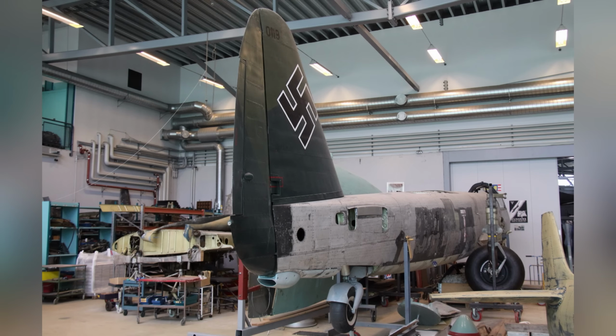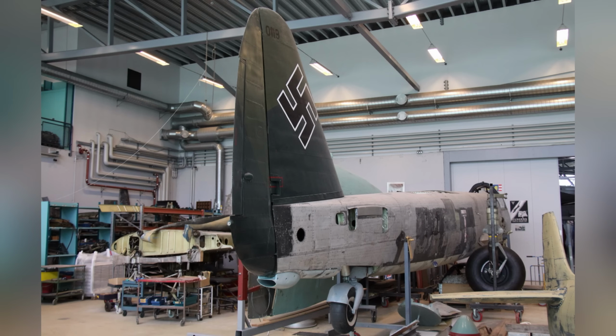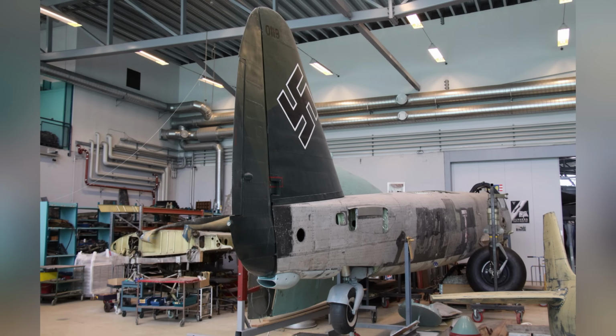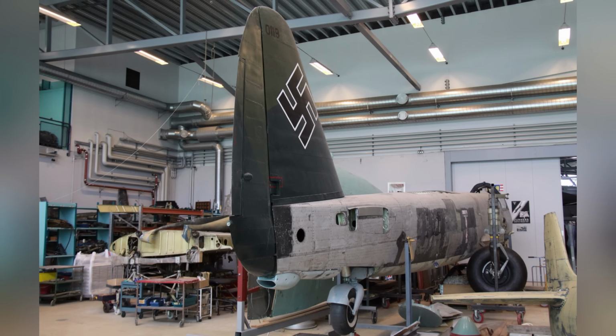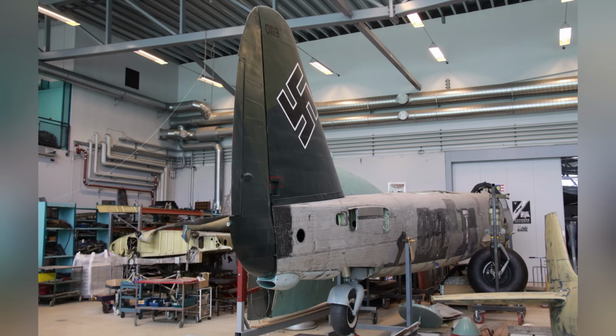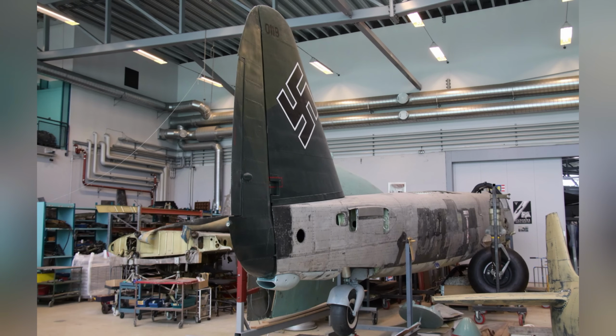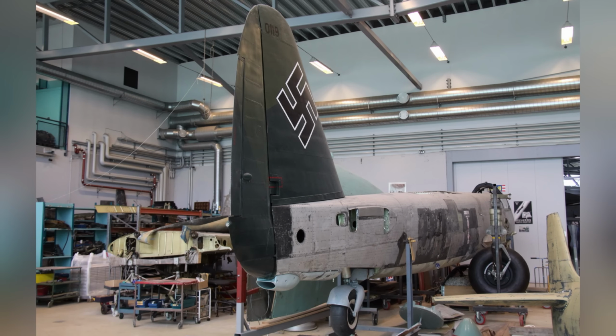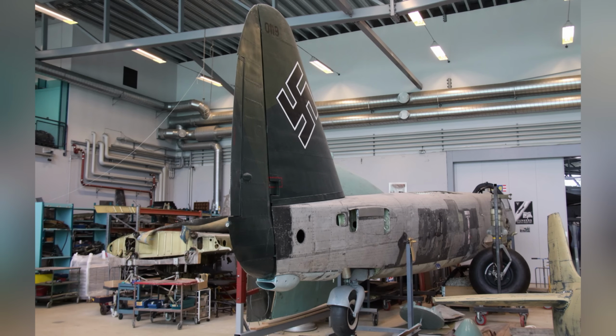The engines and the fuselage are displayed in proximity, but the scars of the lake chemistry are preserved. The point where the magnesium engine mounts dissolved is not hidden or reconstructed with modern metal. It is left as a gap. This void serves as a permanent record of the galvanic corrosion that occurred deep underwater. It demonstrates the interaction between the aircraft materials and the lake environment, teaching the observer about the metallurgy of the era and the specific constraints of the recovery. The magnesium rot is not treated as damage to be repaired, but as a signature of the site itself.